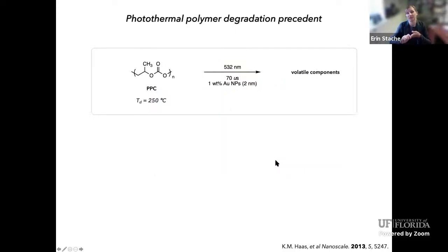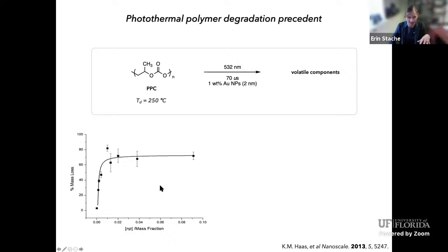There is some photothermal depolymerization precedent. Ben Lear at Penn State published this paper a number of years ago now, where they were able to degrade polypropylene carbonate using gold nanoparticles and laser intensity pulses of light to form volatile components like propylene oxide and carbon dioxide. In this case, they were irradiating a very small film of polypropylene carbonate with these nanoparticles embedded, and they saw they could get about 80% mass loss with increasing gold fraction, which is a really cool application and demonstration that you can use photothermal heating to do depolymerization, or at least polymer degradation.